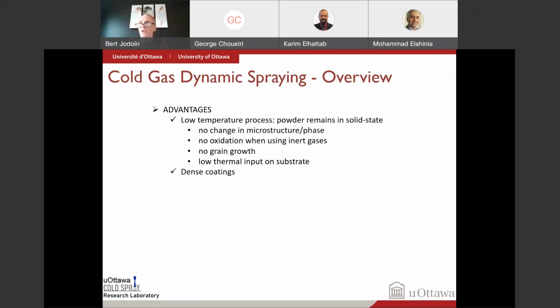We can produce very dense coating. 100% density is always our objective. Sometimes you have a little bit of porosity. Very high productivity. We can produce coatings and parts with tens of pounds per hour as a build-up rate. So that is something very distinctive. We can produce very large parts and very thick coatings quickly. High deposition efficiency. So when we inject the powder, the vast majority of those particles will deform and stick to the substrate. Very few of them will bounce back if the process is tailored properly.